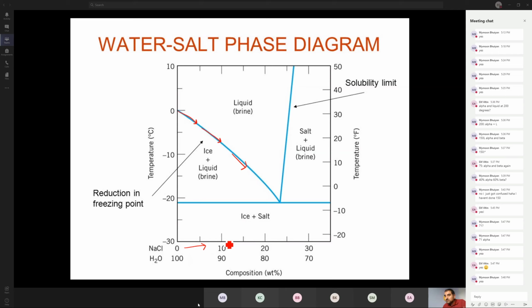So if I spread 10% salt on the road, at -5 degrees, the mixture of H2O and NaCl would be a liquid. It will be brine, so it will melt the ice. If you buy the salt, you sometimes see on it, it will say good down to -20, and another one will say up to -40. Well, it depends on what the salt is. If it's rock salt or sodium chloride, you can see from the diagram, the lowest temperature at which you can have a liquid by mixing salt and ice is -21.